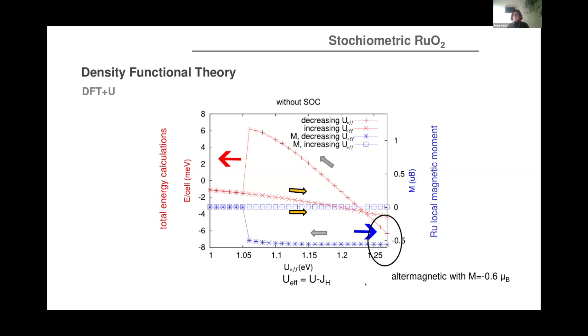So we have done, for instance, constrained RPA calculations for the case of Mott insulators with ruthenium. And the largest value that one obtains for this U effective is of the order of 1 electron volt. Here we are talking about ruthenium dioxide, which is a metal. So that means the screening effects will be important. So we should be talking about, in fact, U effective values that are in this region here, which would correspond to the solution of no magnetic ordering.